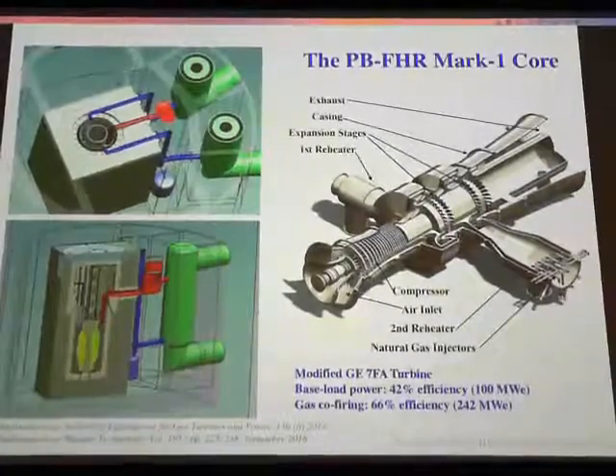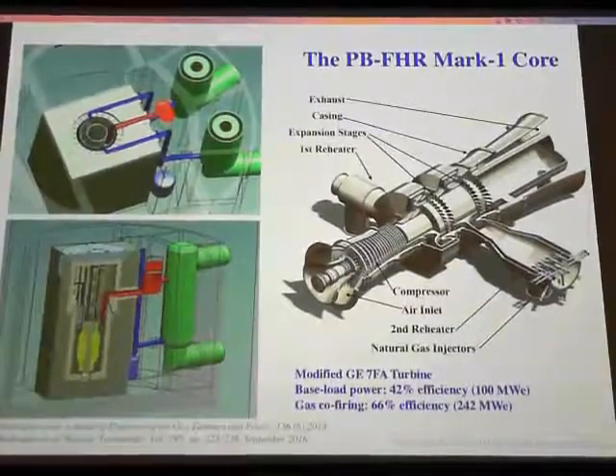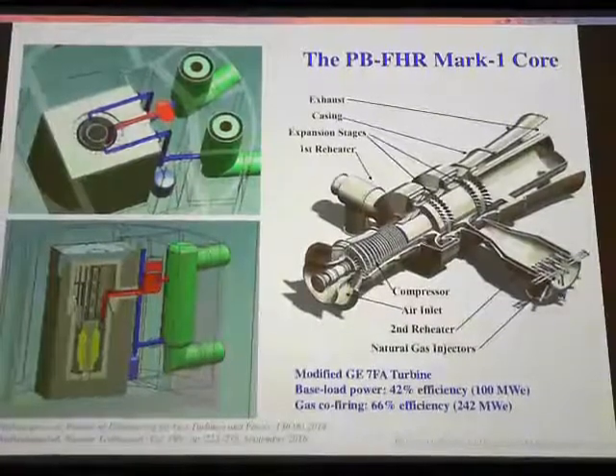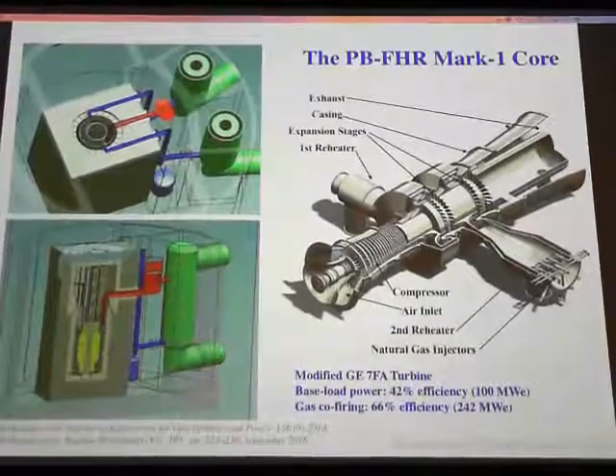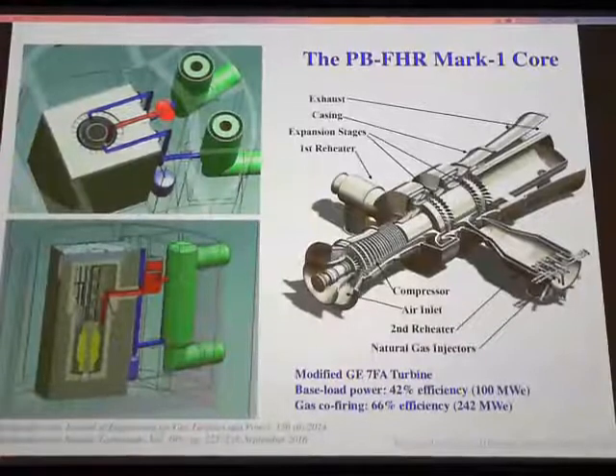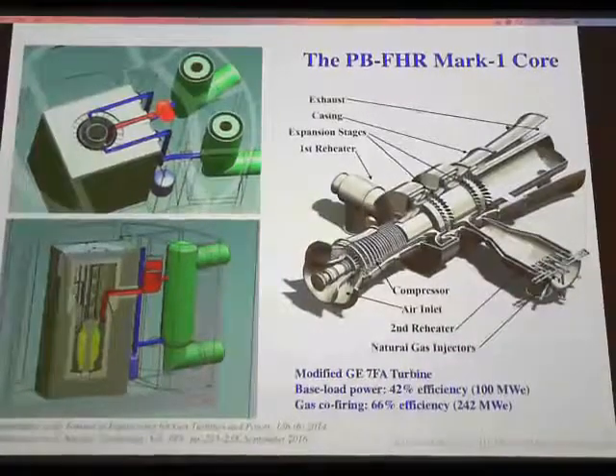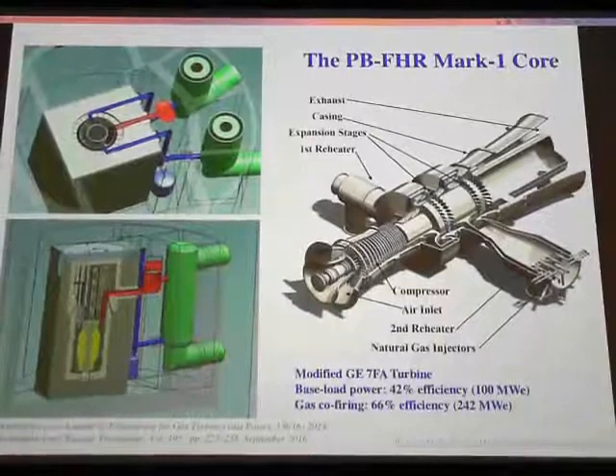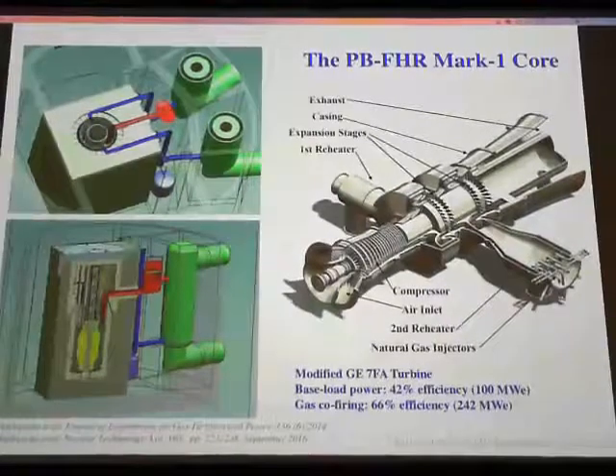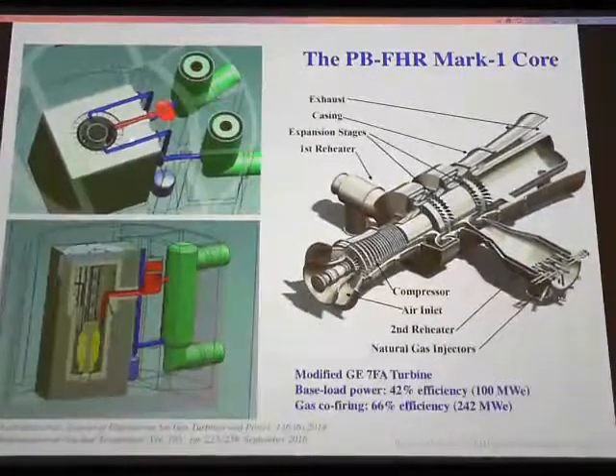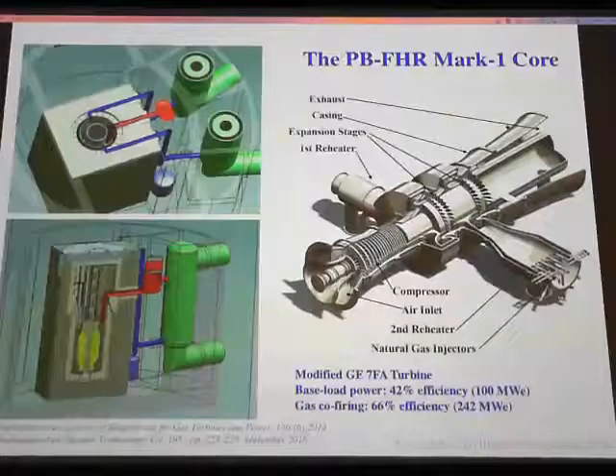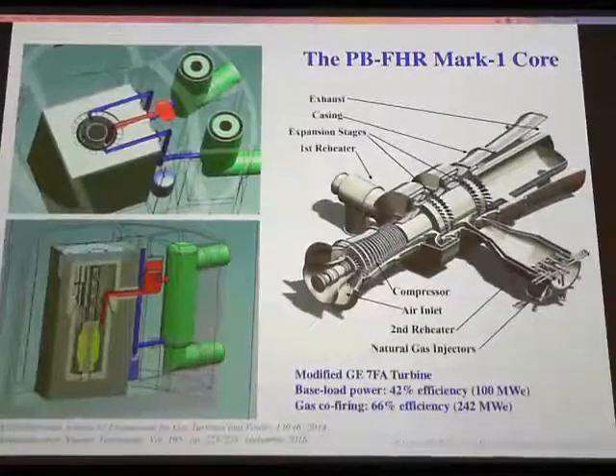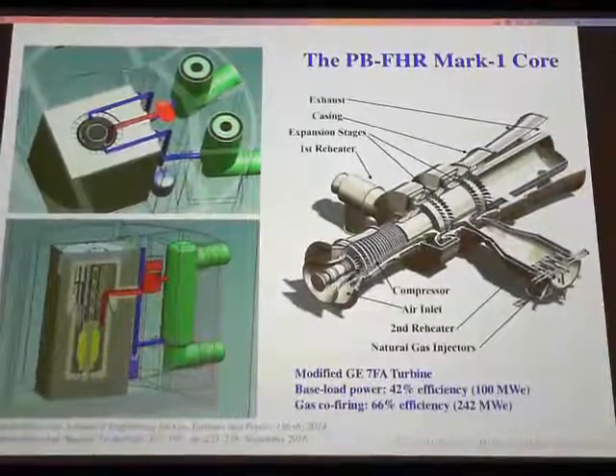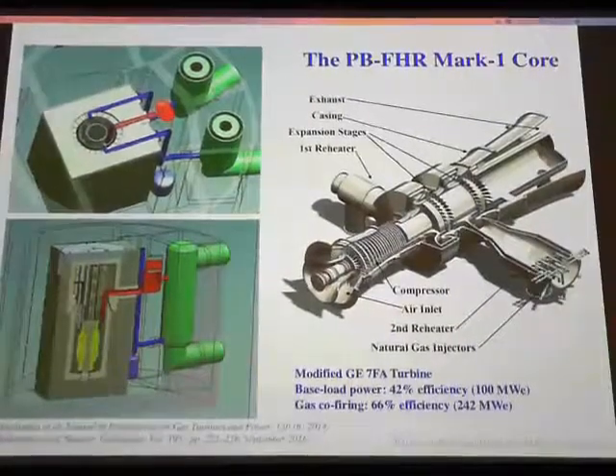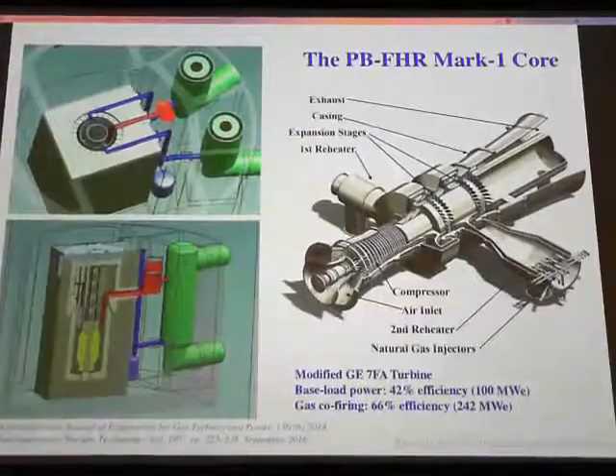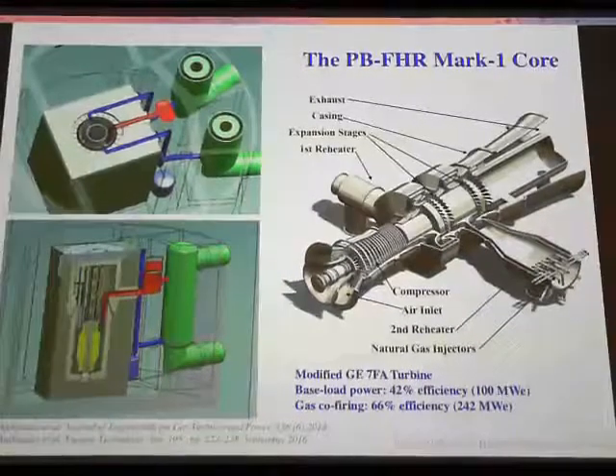The tritium production in coolants is not unique. All reactors produce some amount of tritium of some sort. But what is unique is that we're at high temperatures, and at high temperatures, metallic components are transparent to tritium. So since we have a salt-to-air heat exchanger, the tritium will leak into the air, which will then reach the turbine and be sent up the stack. Since this is an open-air Brayton cycle, you send all the tritium that goes into your turbine up the stack. And so we need a sink for tritium.